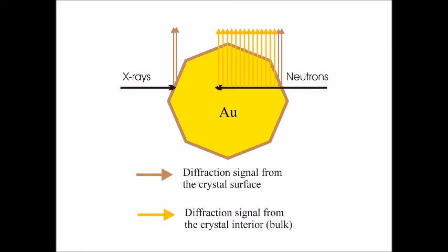Instead of using X-rays to probe the crystallinity of our samples, we turned to neutrons. Neutrons are very penetrating and can go through an entire sample like the ram's horn without having to cut it open. Neutrons will both diffract and absorb in ways that give us information about crystallinity and chemistry, both the elemental chemistry and the abundance of different isotopes of the elements that are present.